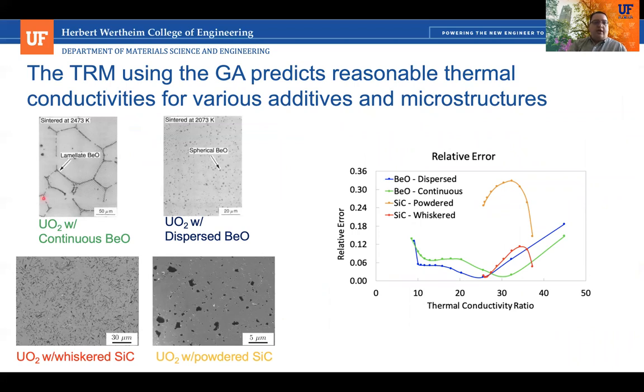So we have UO2 with continuous beryllium oxide and with dispersed beryllium oxide. That's from the Ishimoto paper. And then there's actually two works that were done previously by Chelenko and his colleagues here at the University of Florida, where they have UO2 with whiskered silicon carbide or powdered silicon carbide. So we took these images and we applied the genetic algorithm and then used our effective thermal conductivity model.